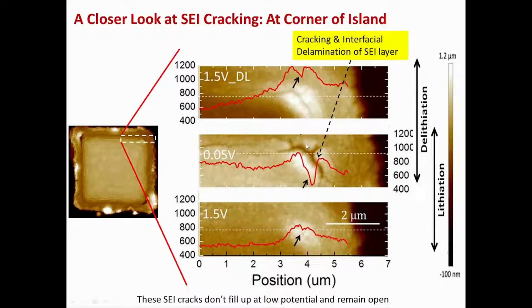Two things to note here: the cracks which form in the SEI layer don't fill up with new decomposition products, which has long been postulated in lithium-ion battery research publications but has never really been seen. So this is really the first ever observation of real-time cracking of the SEI layer, and of what happens after it cracks. The cracks don't fill up completely.